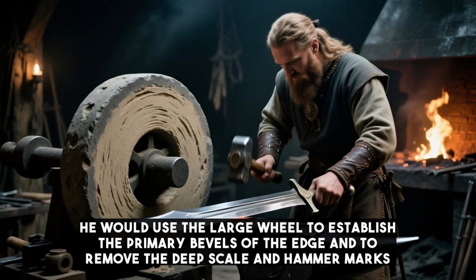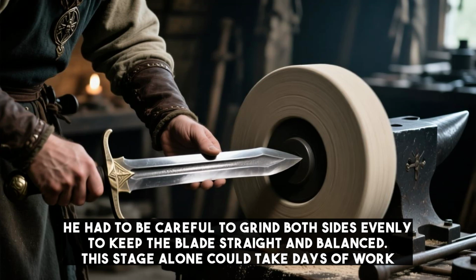If the blade got too hot during grinding, it would ruin the temper, softening the edge he had worked so hard to create. He would use the large wheel to establish the primary bevels of the edge and to remove the deep scale and hammer marks. He had to be careful to grind both sides evenly to keep the blade straight and balanced. This stage alone could take days of work.